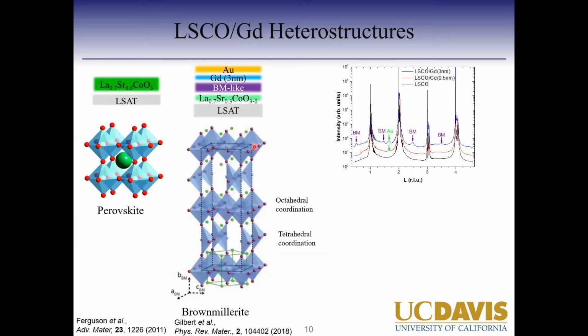So now talking about this oxygen deficient brownmillerite phase, it's essentially an ordered phase where as you create more and more oxygen vacancies, like you're moving oxygen ions out of the system, these oxygen vacancies actually get ordered. So you have the usual octahedral layer, which is present in perovskite. Then the oxygen vacancies result in a tetrahedral layer, and these vacancies are actually ordered along the 110 channel, okay? So they have a very specific orientation. That orientation means that the unit cell of brownmillerite is actually 45 degrees rotated compared to this green perovskite structure.